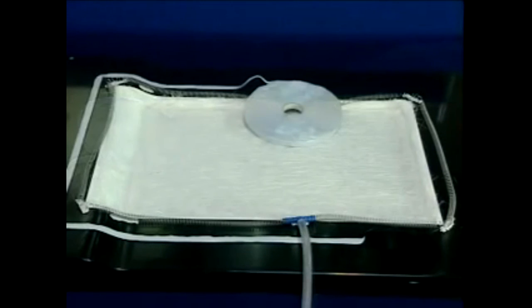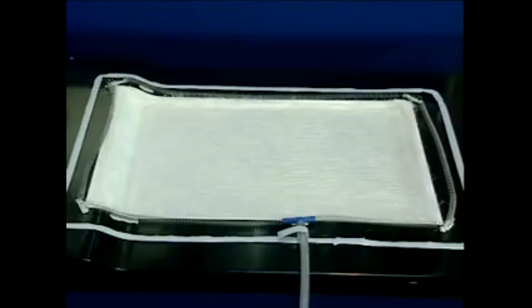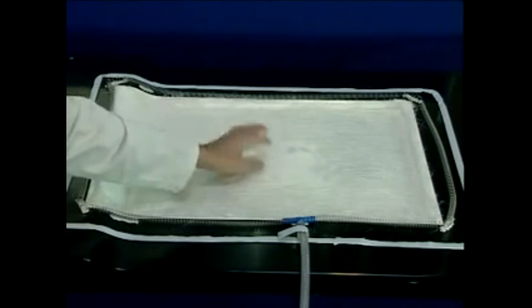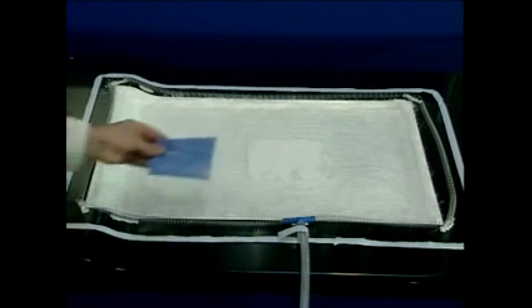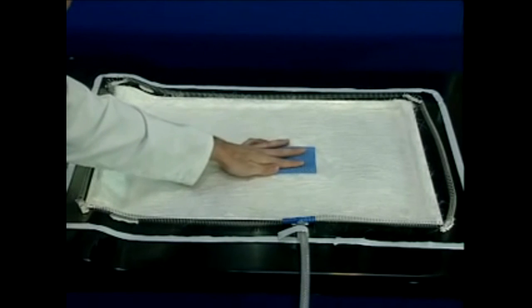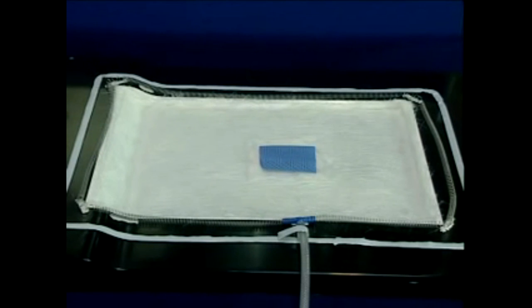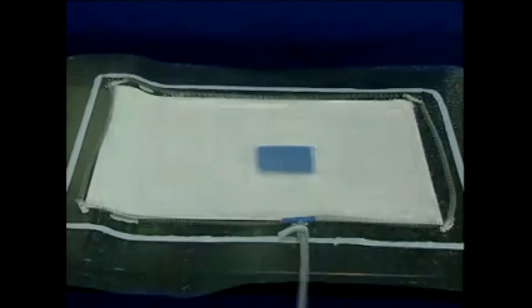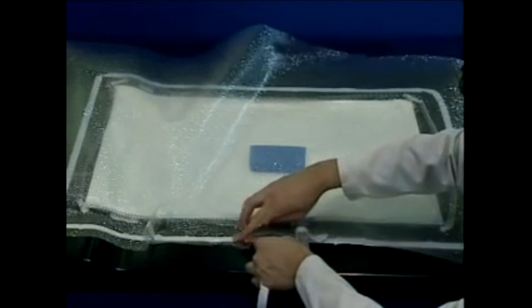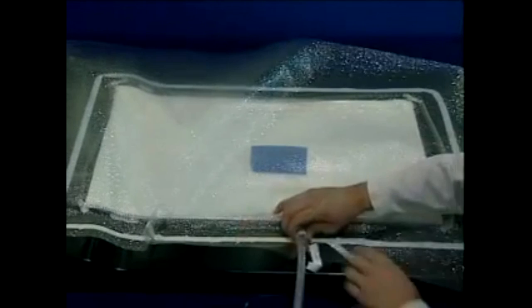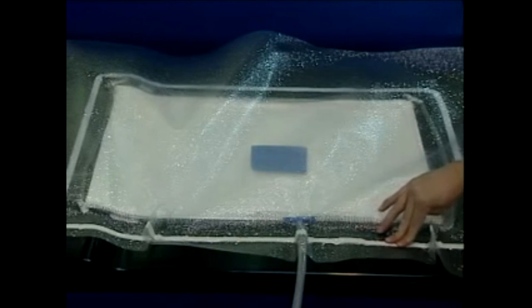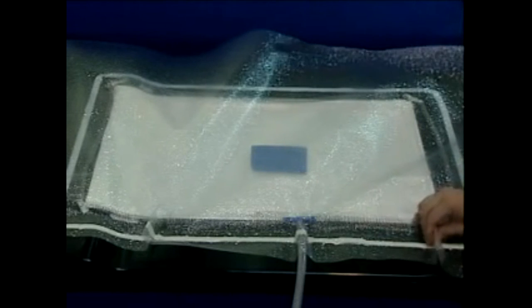Vacuum bagging tape is placed around the mold. The flange should be free of glass fibers, which may create a leak through the tape. Plastic mesh can be used to aid resin take-up at the end of injection, or be used as a gate to distribute the resin quicker across the mold surface. Use of peel ply allows easy removal of this mesh after demolding. The key to vacuum injection is a textured film which allows excellent resin distribution with no additional layers over the laminate. The molder should ensure that there is enough film to take the shape of the molding. Up to 50% more film than molding area may be required.